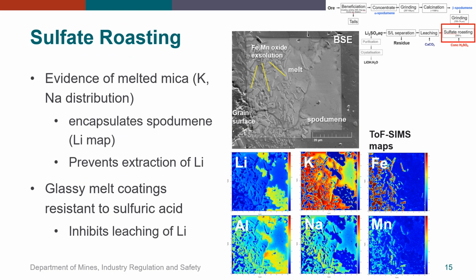Finally, evidence for the refractory effect these glassy melts have is shown in an example of calcined spodumene. A sample of spodumene was calcined and subjected to sulfate roasting and leaching under conditions that simulate what happens commercially. The leached spodumene residue was then characterized and element distribution mapping performed using high-resolution time-of-flight secondary ion mass spectrometry, TOF-SIMS, which is capable of mapping very light elements such as lithium.